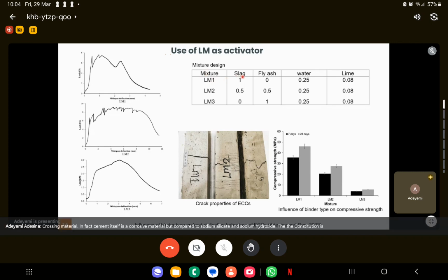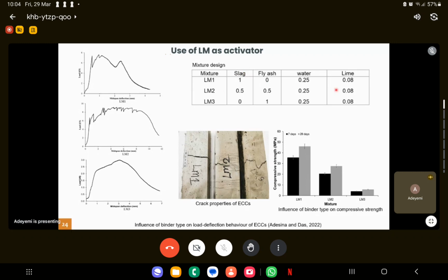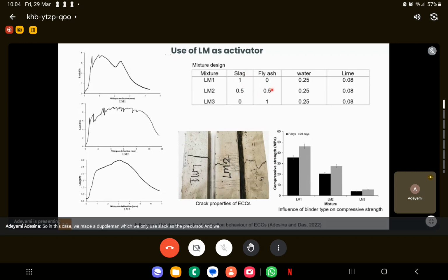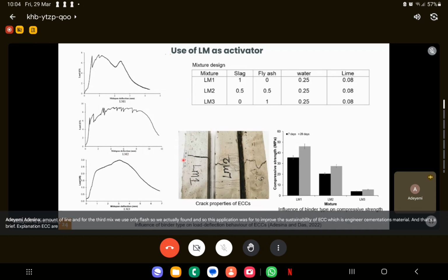So in this case, we made a geopolymer in which we only used slag as the precursor, and we used lime. Then the other one we used a combination of fly ash and slag at the same amount of lime. And for the third mix, we used only fly ash. This application was to improve the sustainability of ECC, which is engineered cementitious composite. As a brief explanation, ECC is a fiber reinforced material which has a higher tensile capacity. The tensile capacity of ECC is about 100 times that of normal concrete, so it's pretty huge.